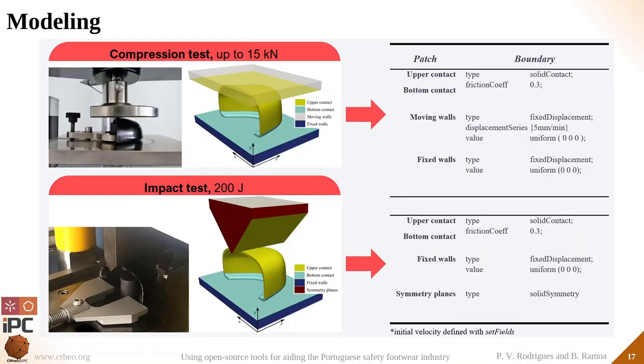As for the boundary conditions, the top of the moving plane was defined with a fixed displacement moving at 5 mm per minute. The bottom of the plate was set with a fixed displacement, with zero displacement in all Cartesian directions. The contact between the toe cap and the plates was defined with a solid contact boundary condition, and we used a coefficient of friction of 0.3 and a penalty scale value of 0.02.